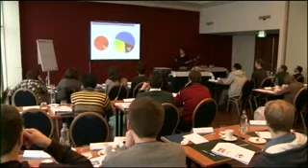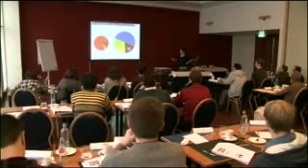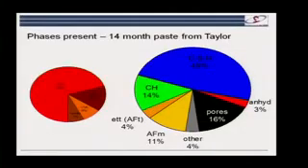You see at the end of this 14 months, we have about half of this compound C-S-H. We have some anhydrous material that hasn't reacted. We have calcium hydroxide, which is a very important phase. We have these two AFm, AFt phases down here, and we have porosity. So porosity is always very important. I'm not going to talk in detail about porosity today because that's the subject of the lectures on Wednesday morning.